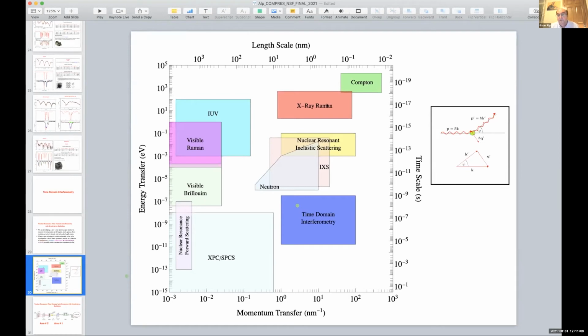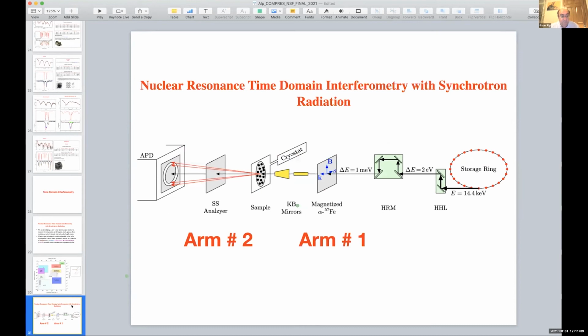X-ray Raman, you're more familiar with that. There is inelastic scattering in the meV range, but this region here is not so full with different alternatives. So the region we are covering now in the time domain interferometry is a relatively empty region where XPCS cannot reach because of the large momentum transfers, and yet we can provide you information there.